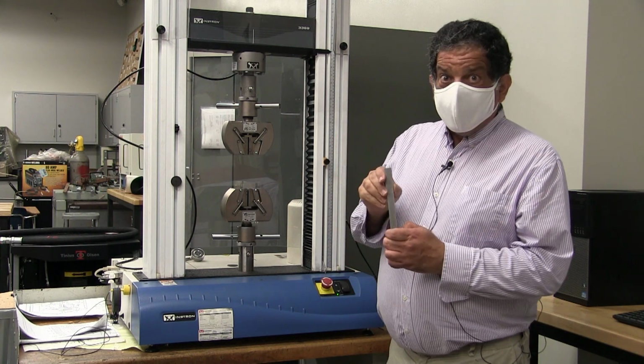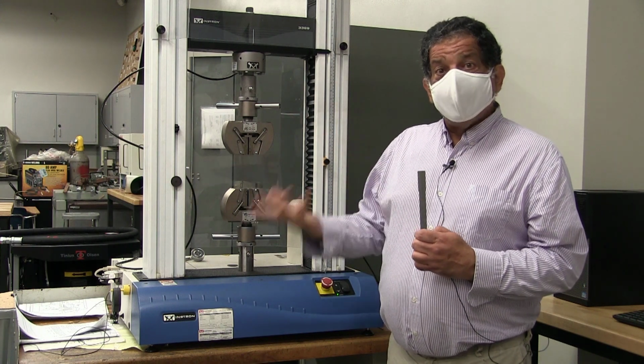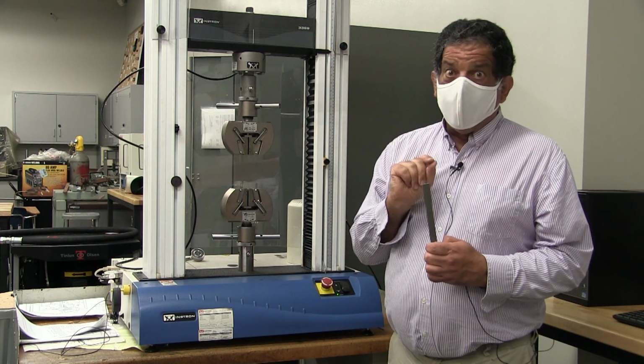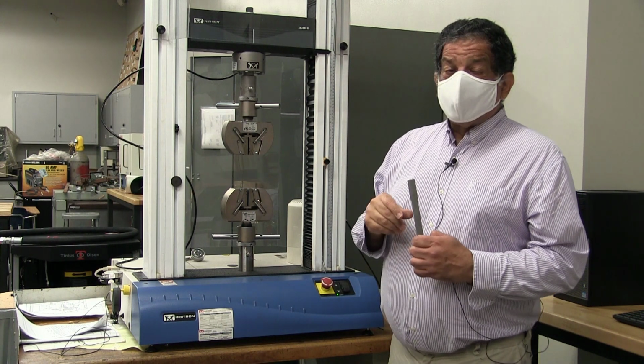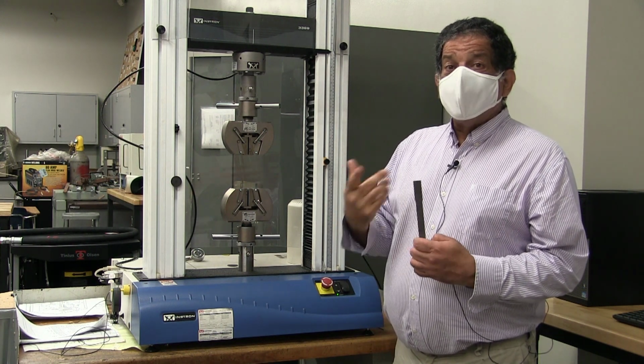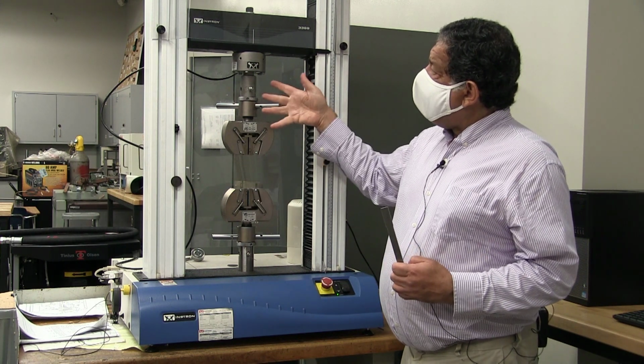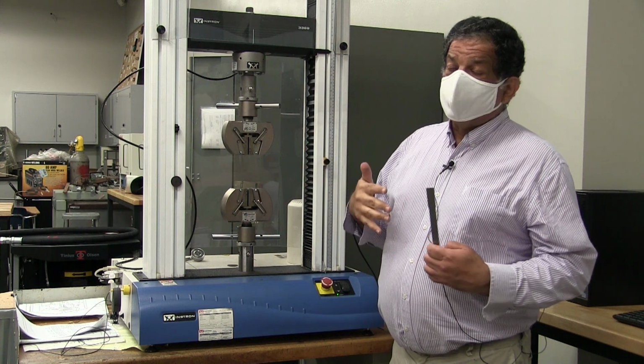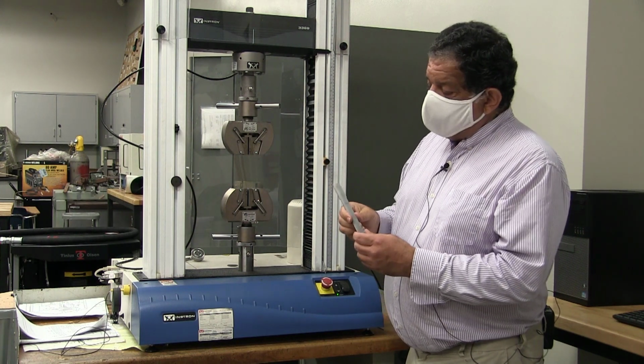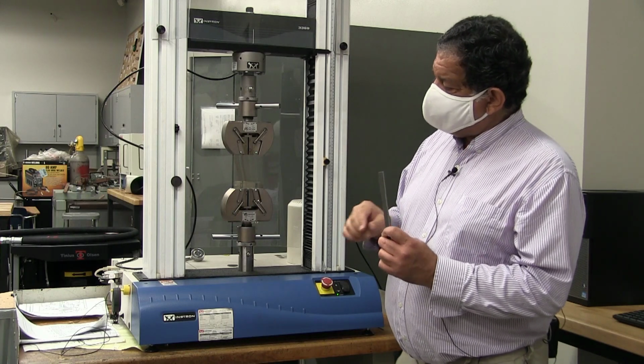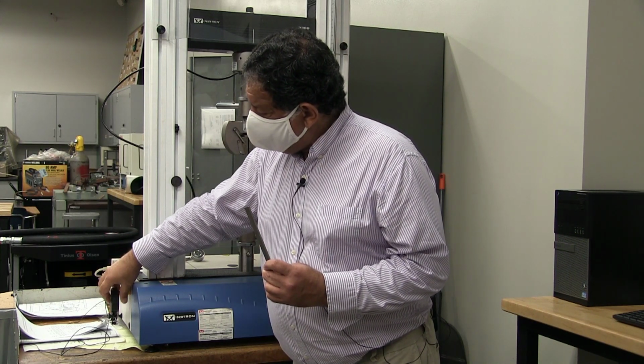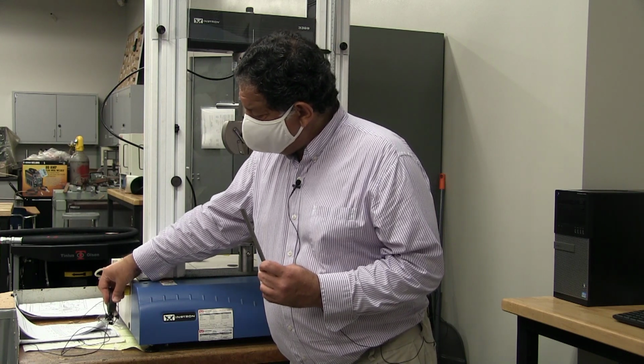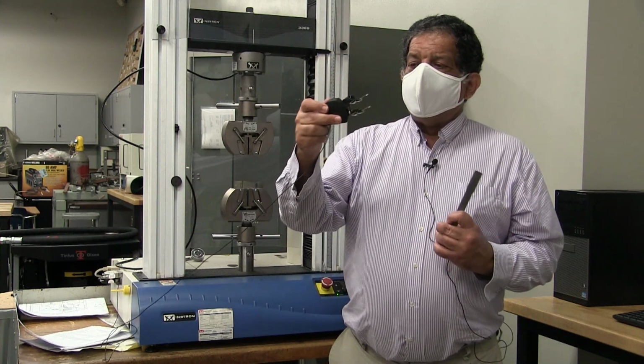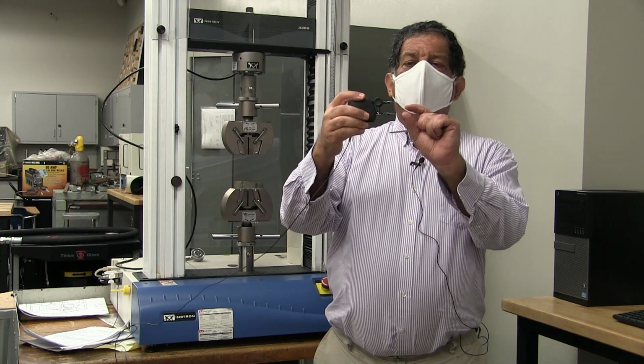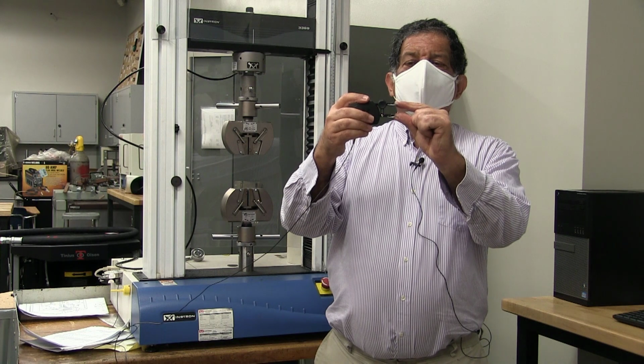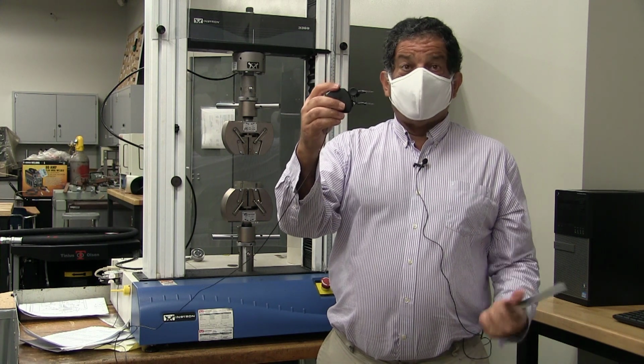But if you need accurate measures of strain, like for example for determining the yield strength of the specimen, you need the 0.2% offset. In order to measure the elastic modulus of the specimen, you need very accurate measures of strain, and if you have that compliance of the load train built in, you'll get large errors. So when we want super accurate measurements of strain, what we're going to do instead is use a delicate but very accurate machine called an extensometer. This extensometer has two jaws that travel only a very short distance apart, but over that short separation distance, it's super accurate.